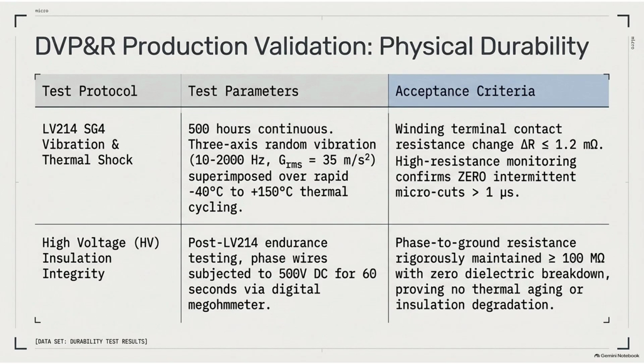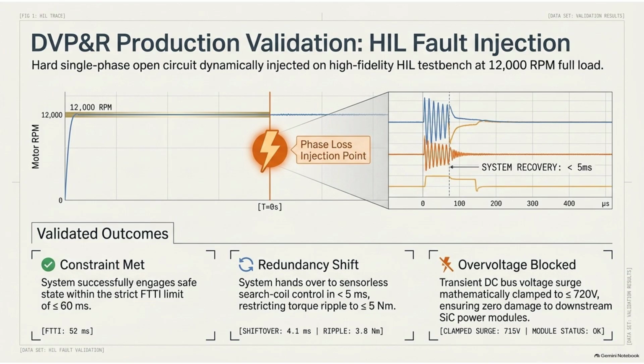What happens in that test? They take the battered, thermally shocked stator, hook it up to a testing rig, and blast it with 500 volts of direct current for a full 60 seconds. They are intentionally trying to force the electricity to arc through the insulation. Exactly. They measure the resistance of the insulation, the epoxy that was vacuum sealed and scanned for bubbles earlier.